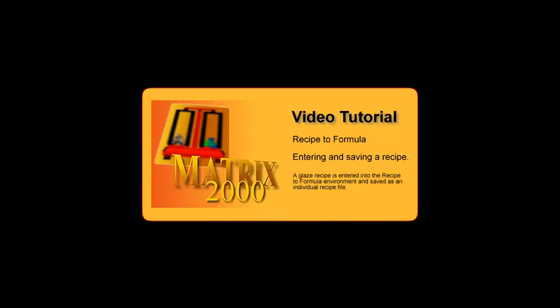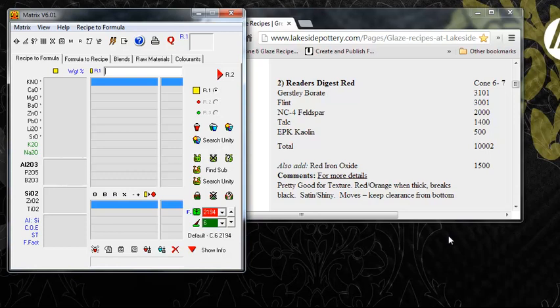For this demonstration, I have displayed a cone 6 recipe taken from the internet. It uses a feldspar not included in the local materials database. The first check is to look at the temperature setting to make sure it is set for the firing temperature of the recipe. The next thing to check is the firing atmosphere. In this case it should be oxidation.